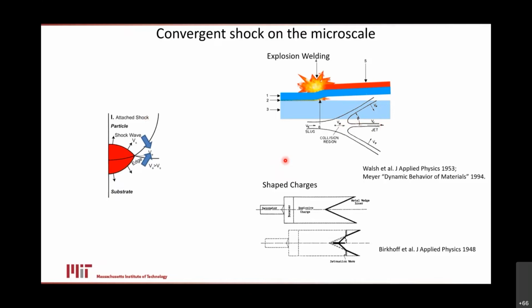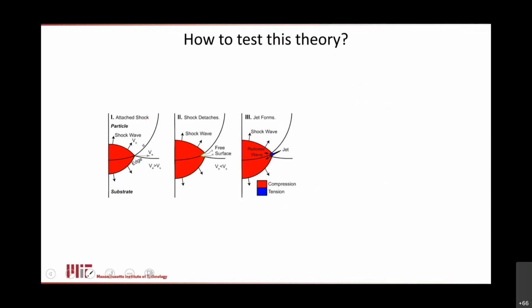So we see this microparticle situation as just being a micro shaped charge or a micro explosion weld. We're smacking those guys together and they're shooting out jets. And in fact, the mechanism then is the same one as in those cases. The shock waves detach from the free surface. We flip a state of compression into one of tension, and you get a jet shooting out in what is essentially a spall-like process, right? This is almost like a shock spall type process where we're shooting out a jet. So that's the way we view this phenomenon, and we have quantitative tools to study it now.